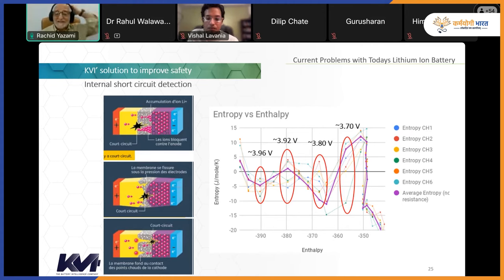So on this slide, on the right side, for instance, I can drive the voltage of this cell to 3.7 volts and then measure entropy at that point. It's very simple. It can be done very fast, in a couple of minutes. And then I compare the data that I'm collecting at 3.7 volts. If the data fall on the solid line, which is the pink line, there is no internal short circuit. If it departs from this data, there is an internal short circuit.